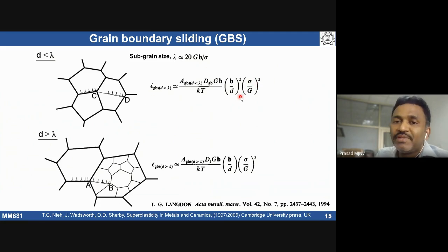Most superplastic materials need to have a fine grain size, close to equivalent to the subgrain size. Then typically we see this kind of constitutive equation. It is going to have grain boundary sliding along with dislocation creep, where climbing activity can take place. That means grain boundary sliding accommodation is going to be done by dislocation creep.